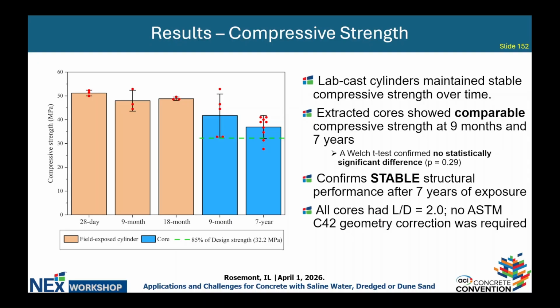Most importantly, we have the extracted cores, extracted from the test blocks themselves. We have them after 9 months as well as 7 years. They showed comparable performance in terms of the compressive strength. To confirm this conclusion, we conducted a Welch t-test in order to determine if there is any statistically significant difference between the two groups. The results confirmed our conclusion, which means that after 7 years of having seawater concrete under real marine exposure, the structural performance stays stable.